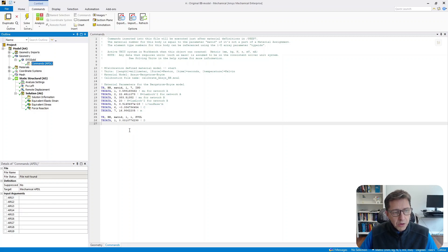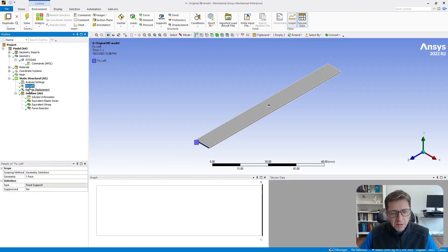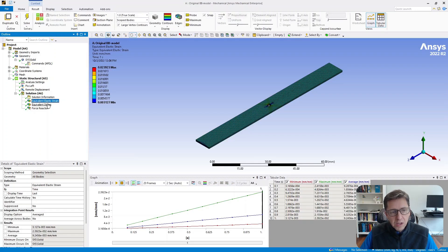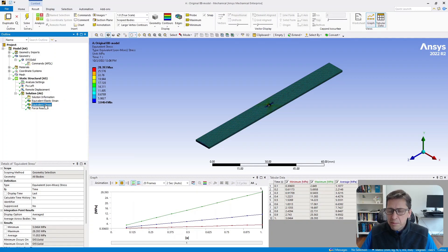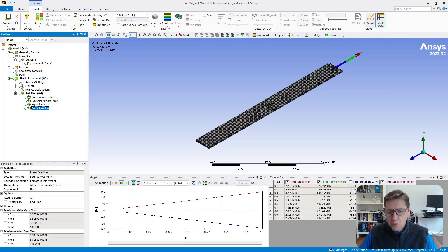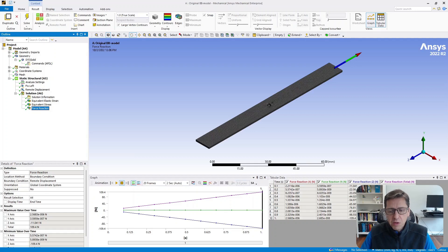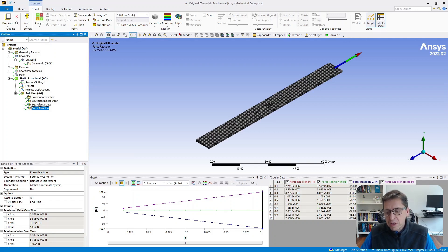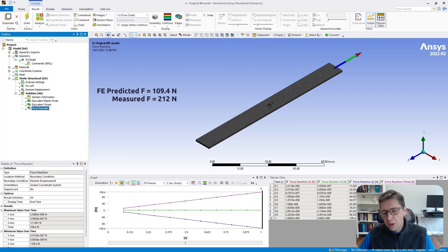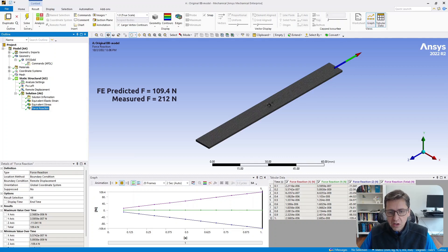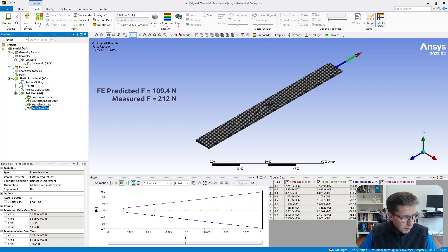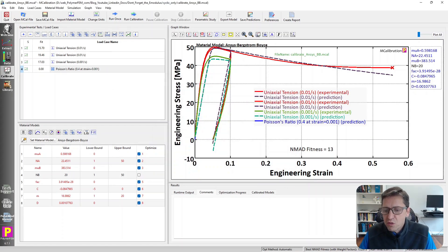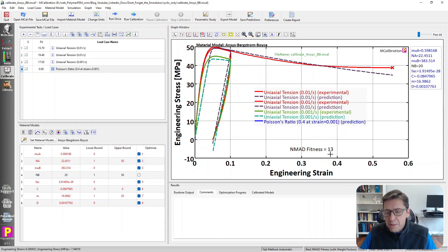And what I do after that, I just apply my boundary conditions. So I keep the fixed left and I'm pulling on the right. And if I perform the simulation, you can look at stresses and strains. But I was focusing here on the force because I have measured the force experimentally. My simulation gives me a force of 109.4 newtons. And the actual value here is, when I ran this experiment, was 212 newtons. So the prediction is absolutely terrible. We got predicted 100 newtons and there should be 200 newtons. Clearly, this is not a 13% error that we saw back in MCalibration. So this is the dilemma that I wanted to focus on in this video. The error that can be much larger in the end than what you think from this error here.